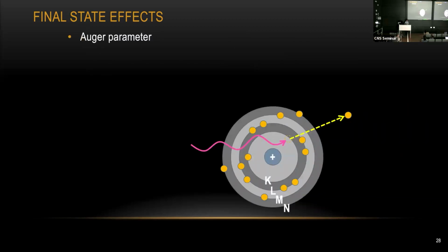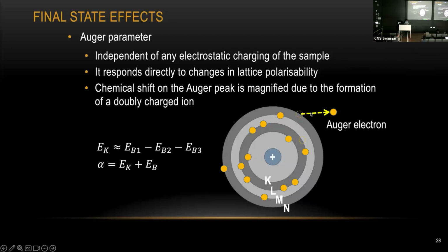Earlier, I mentioned that during the XPS measurement, you're going to pick up some Auger signal. And why do we see the Auger signal? That's what the cartoon is showing here. If the X-ray comes in and knocks out one of your core level electrons, the system is not stable. One of the higher level electrons might fill in the lower level, but it's still not very stable. So eventually, the outer shell electron will leave the atom, and we call this electron an Auger electron.